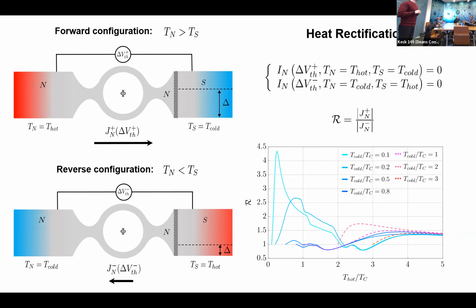However, independently of the parameters, in the superconducting regime, so when T cold is very, very small, you almost obtain this very high rectification. It's not of the order of 4 or 4.5, which corresponds to this 350%, but it's pretty big. At least it's bigger than 100%. But of course, the system is highly nonlinear, and so by really changing the parameters of your junction, you can get whatever result. But it's good that you can control it. So basically, once you have the sample, you control your external parameters, and for sure you get good rectification.